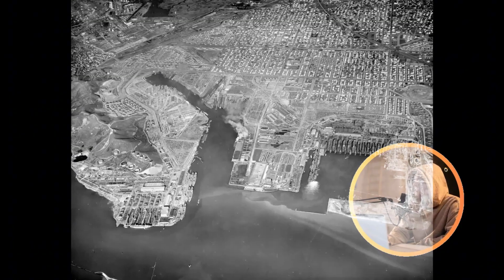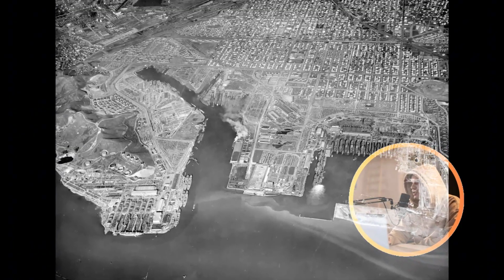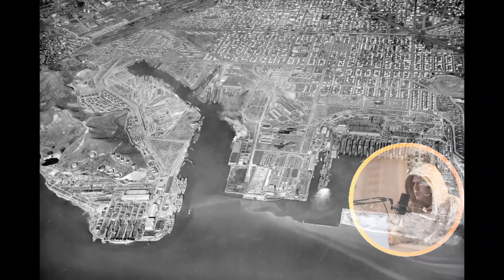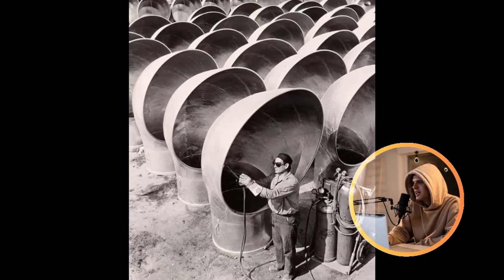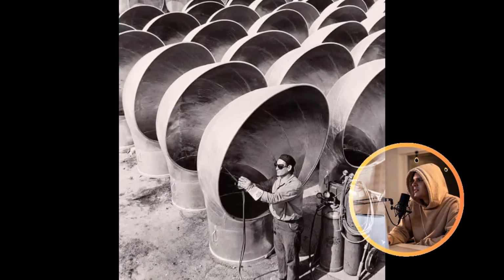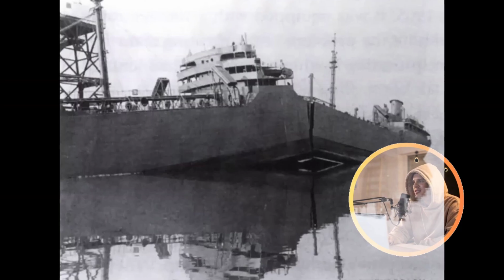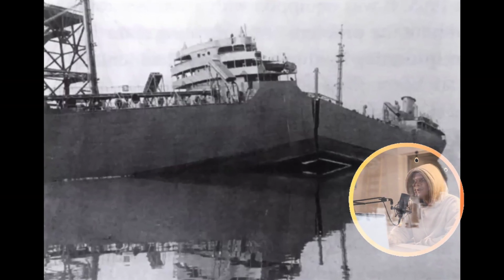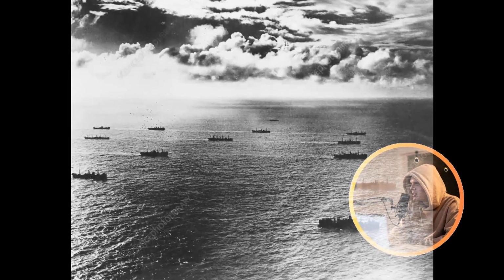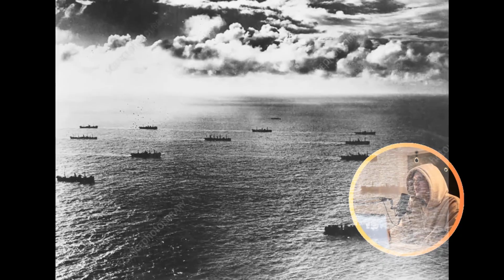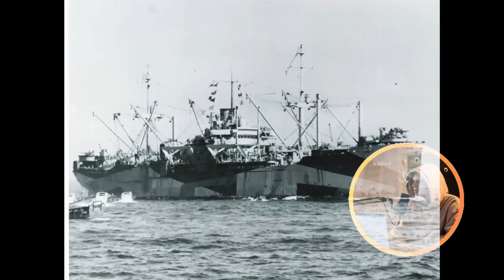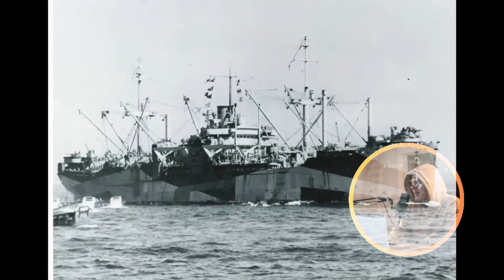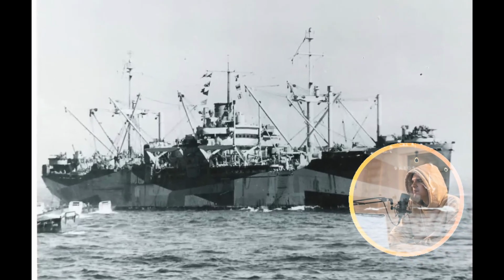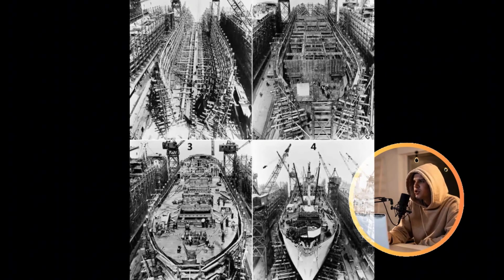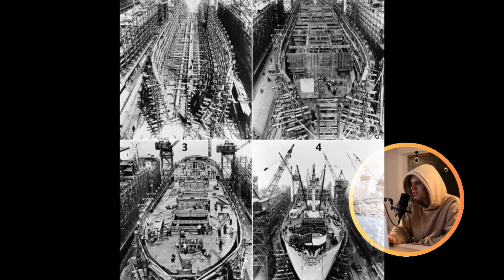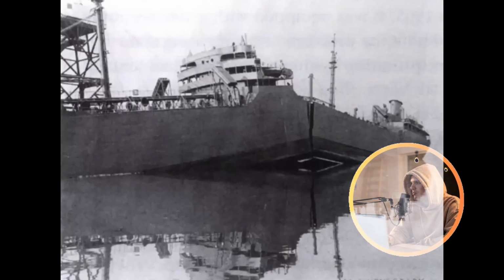Liberty ships were suffering from a phenomenon metallurgists term brittle fracture propagation. The specific type of steel utilized in their hulls, a carbon steel designated as shipbuilding grade, performed adequately in warmer waters. However, it underwent a critical and dangerous transformation in the near-freezing temperatures of the North Atlantic. Below approximately 40 degrees Fahrenheit, the steel's crucial ductility dramatically collapsed. Normally, metal absorbs stress by deforming slightly, bending rather than fracturing. Cold steel, however, loses that vital flexibility. It becomes brittle, behaving more like fragile glass than the tough, resilient material welders worked with in California's mild shipyards.